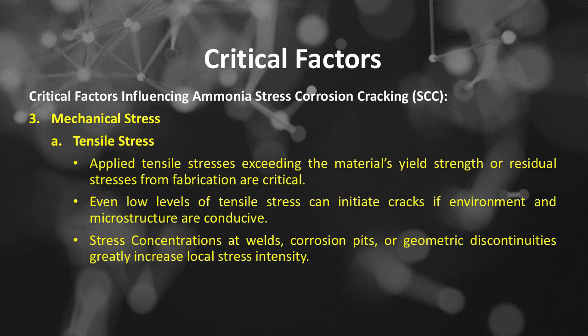Critical factors. Number 3 is mechanical stress, includes, number A, tensile stress. Applied tensile stresses exceeding the material's yield strength or residual stresses from fabrication are critical. Even low levels of tensile stress can initiate cracks if environment and microstructure are conducive. Stress concentrations at welds, corrosion pits, or geometric discontinuities greatly increase local stress intensity.